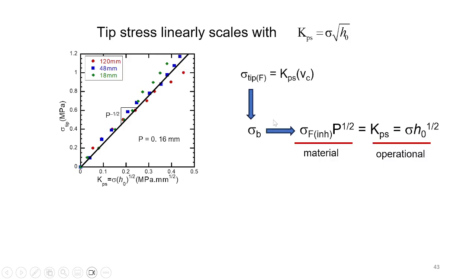The most remarkable thing out of this was that you are able to find that the tip stress grows linearly with this parameter called K that I introduced initially, which basically is the far field load. So this linearity tells us the tip stress just linearly grows with far field load. In fact, you can look at the point where crack propagation occurs, and if you regard that as the material property, then this linearity naturally produces a length scale, which is the material property related to basically how the stress intensifies at the crack tip.